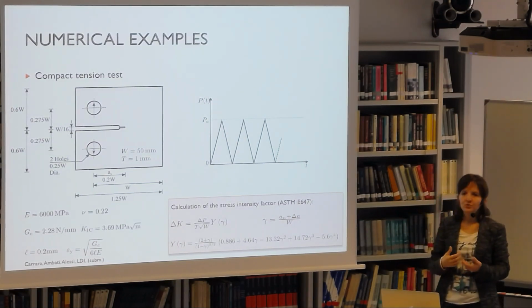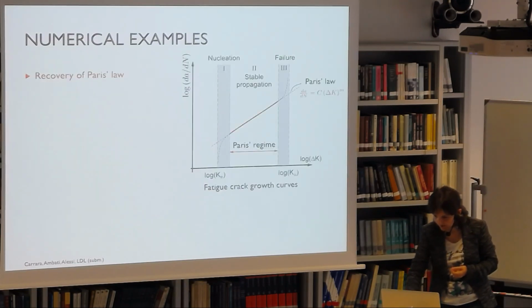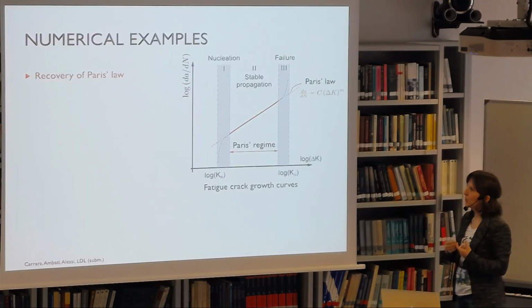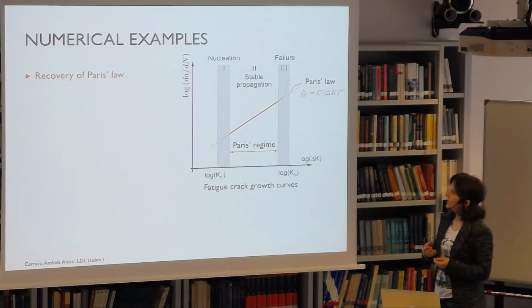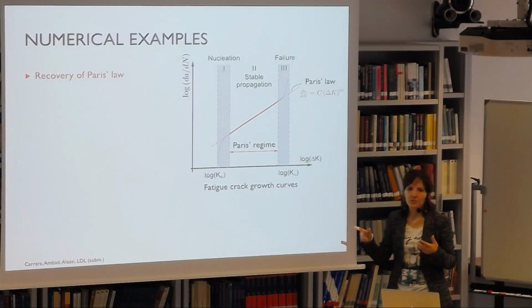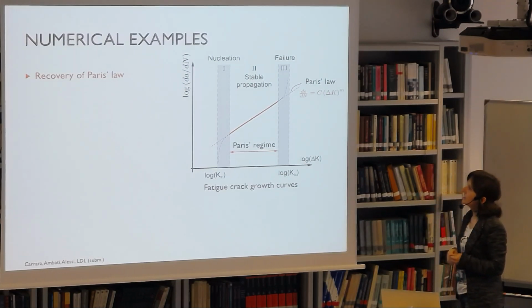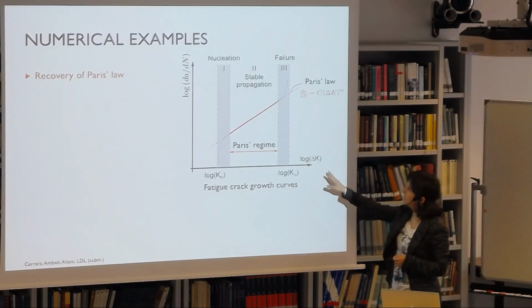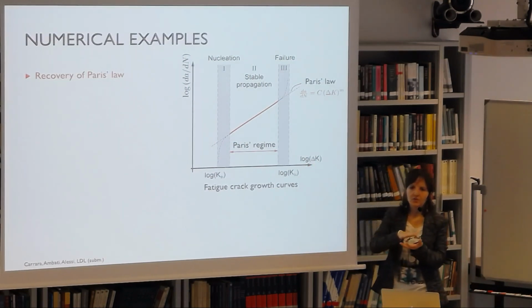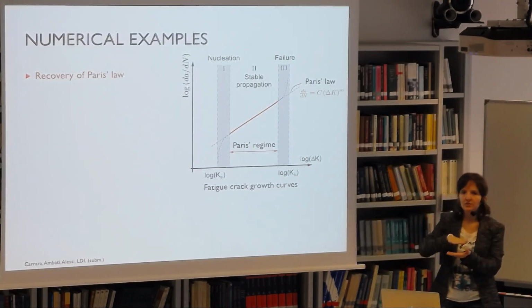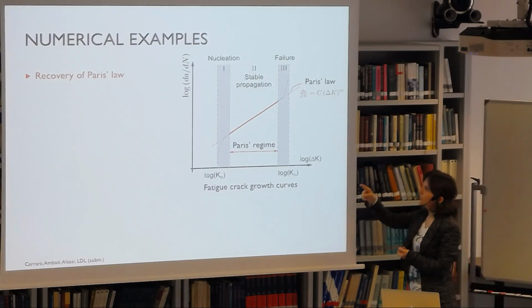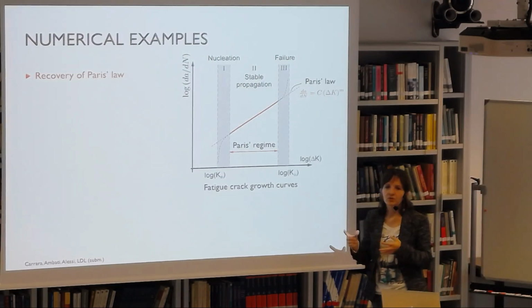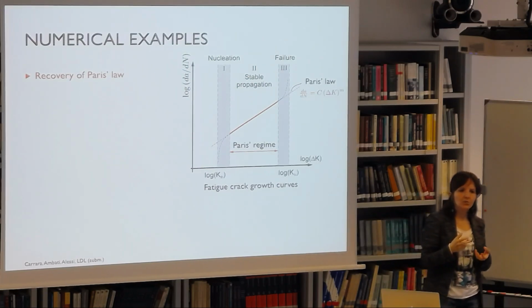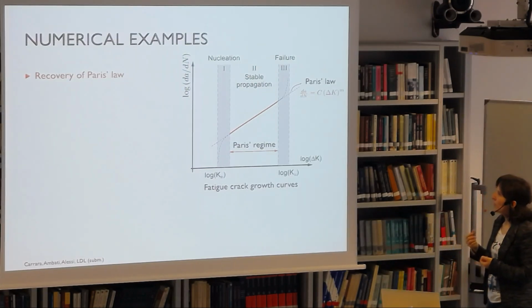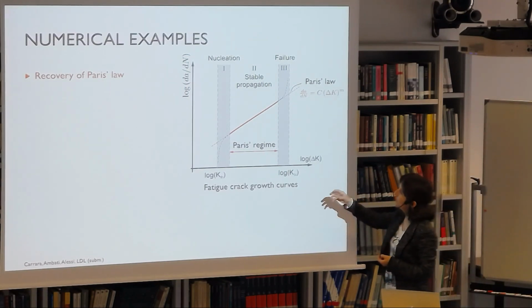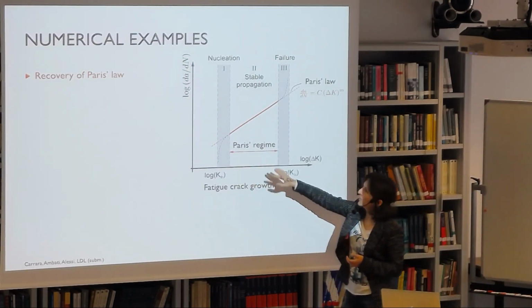And so what we want to see is if we can recover the expected behavior with this approach. What is the expected behavior? Paris took a lot of experiments on fatigue, and he plotted on the x-axis the logarithm of delta K, so the amplitude of the stress intensity factor along the cycles. And on the y-axis, he put the logarithm of dA/dN, so the rate of propagation of the crack with the number of cycles. And what he found out is that there is an initial phase that corresponds to nucleation,